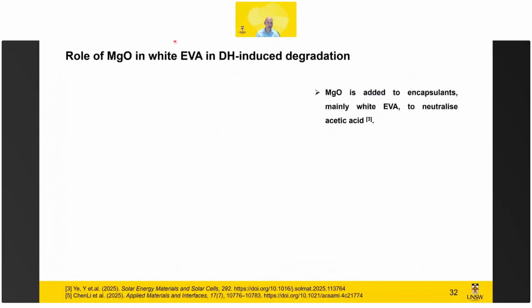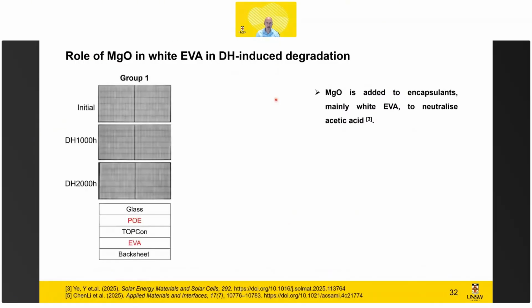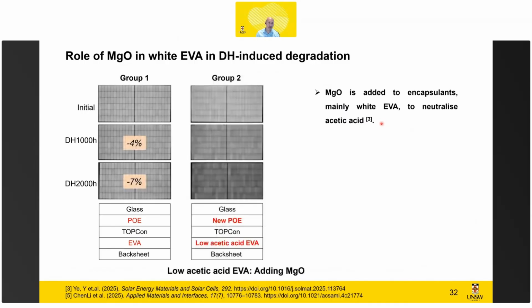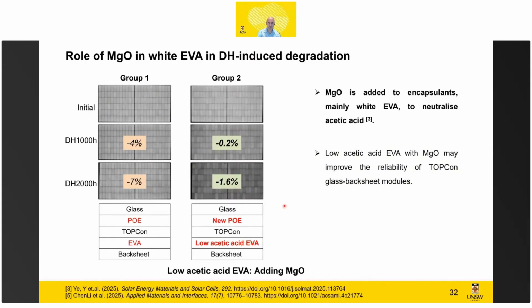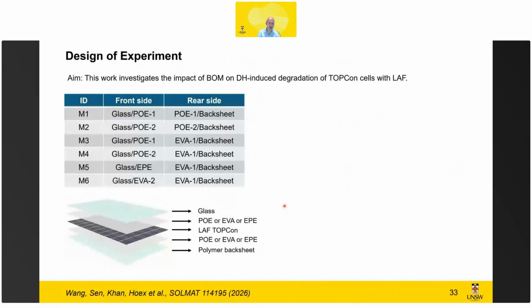Then another additive we looked at was magnesium oxide, which is a typical acid scavenger. So if you have EVA, when moisture gets in, you get acetic acid. But you can actually include that, and then you can use acid-scavenging encapsulants, and you can actually have better performance. So that's shown here. Just by changing the rear EVA to EVA with the acid scavenger, you see that the loss is a lot less. So it goes from 7% to 1.6%. So that's very good. But we saw something interesting when we did a big split in this experiment.